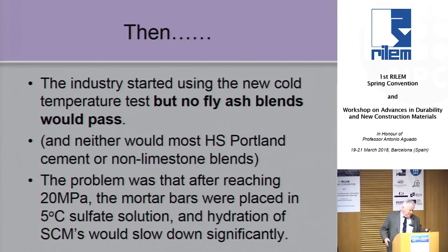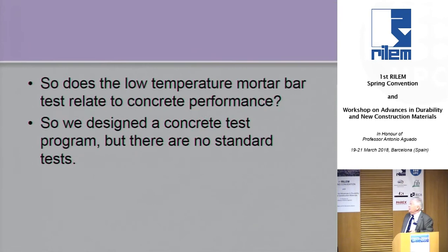But as I said, this test method we put in 2010 caused all kinds of problems in the industry when they started using it, because many of the western areas where the high sulfates are, they don't have slag, they have fly ash. And of course, the test method didn't show that to work very well. So we said, well, are we really simulating concrete performance? So we started doing concrete testing.